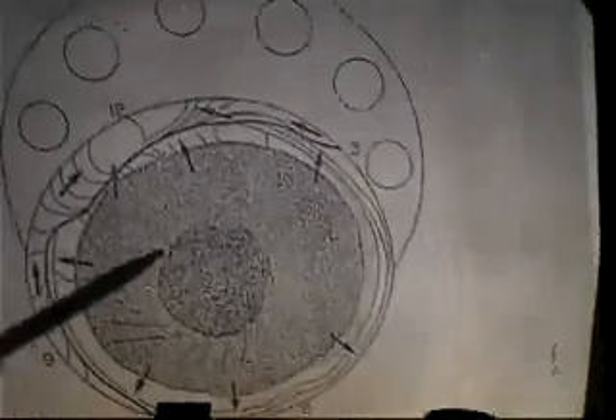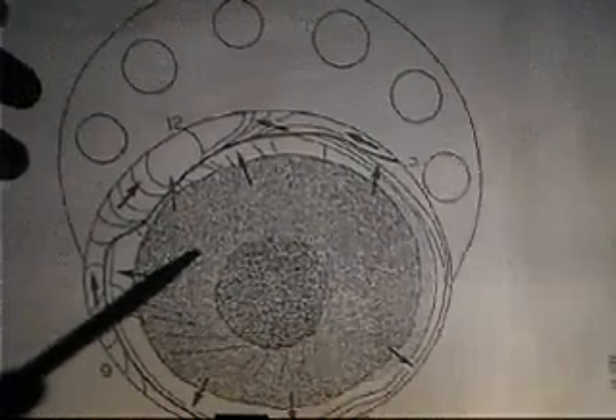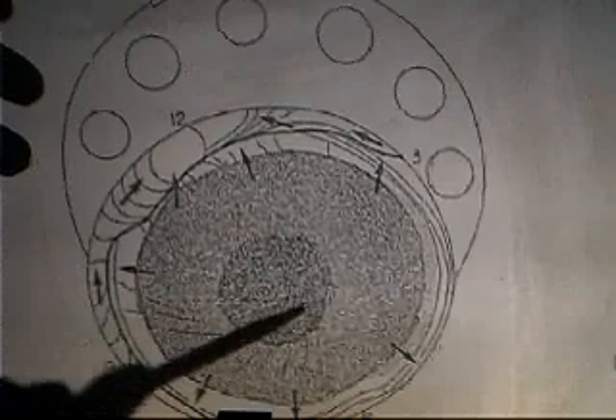If you actually look at the cracks, and this is the microstructure, the grain structure of the steel, you actually see the porosity and you see the cracks running between the partially forged porosity in these things. So if you then produce a fracture map of this thing, here's our big void in the center, and it turns out this rough area in here was actually another forging defect. This was a casting defect, the hole in the center was a casting defect that was produced from the center pipe.